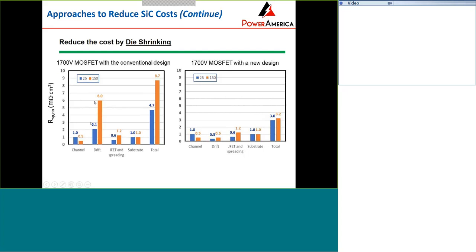The left figure shows the specific on-resistance from the different components: channel, drift, JFET, and spreading and substrate. The total specific on-resistance at room temperature of the 1700 volt MOSFET demonstrated is 4.7 milliohm centimeter square. When we increase the temperature to 150 degrees C, the specific resistance increases to 8.7 milliohm centimeter square. As you can see, the drift component is dominant for the 1700 volt MOSFET, especially at high temperature. If you could optimize the drift by superjunction, or some different new approach, you could reduce the total resistance from 4.7 to 3 at room temperature, and to 3.2 at high temperature. So it could potentially reduce the chip size by more than half.